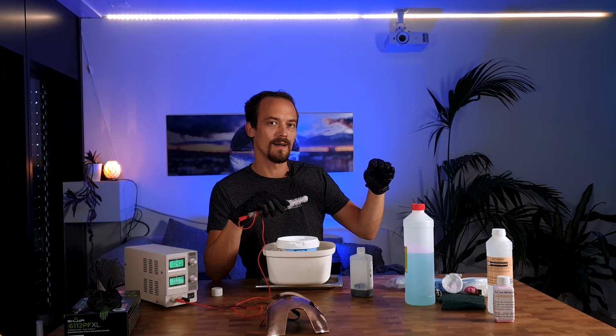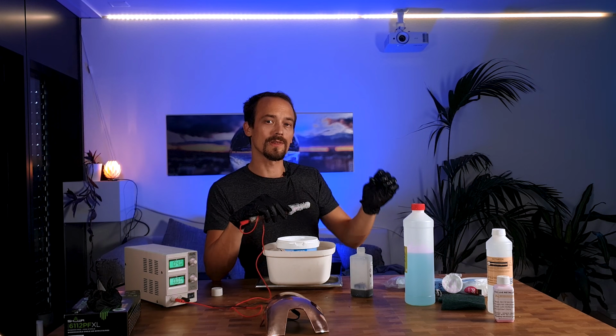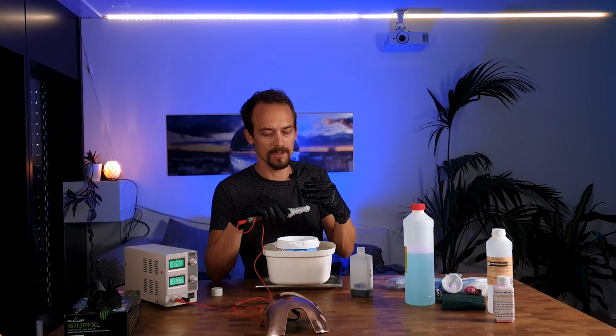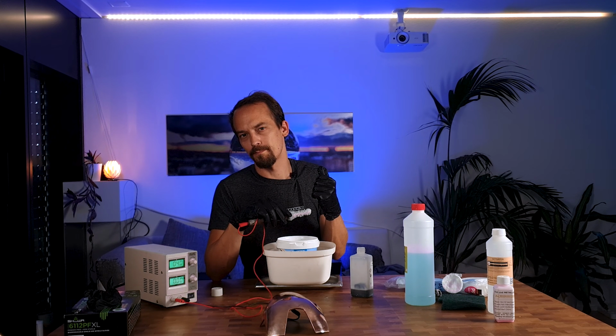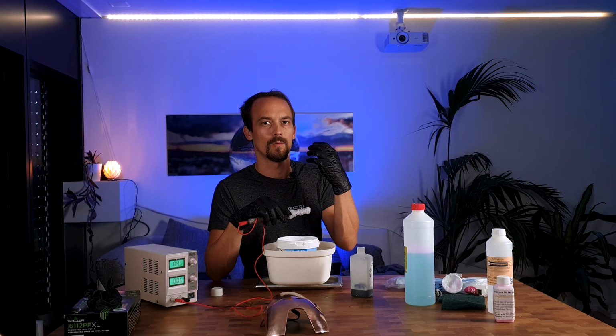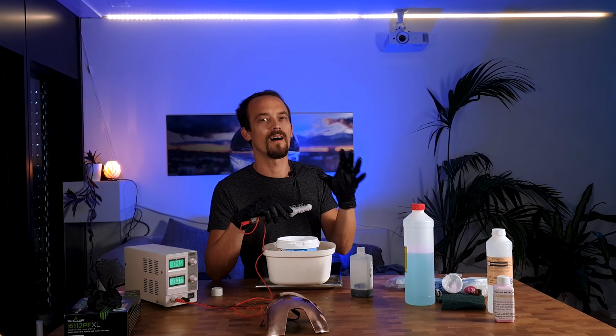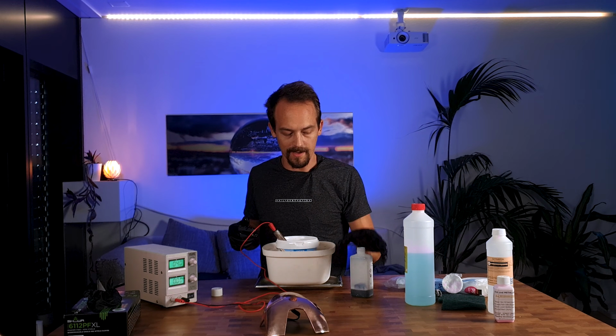So if you have a nickel layer and you put your gold layer on top, the gold will adhere to it a long time and will stay shiny and glossy even if you use it. If you don't have a nickel layer, if you, for example, use graphite and then gold plate it directly, the gold will basically scratch easier, wear off easier than if you have a hardened nickel in between. So let's start nickel plating and see how it goes.